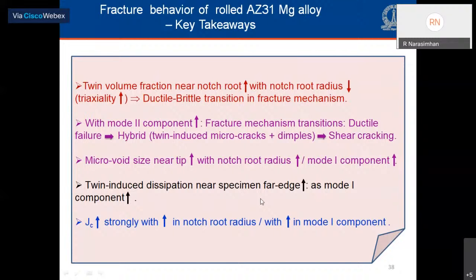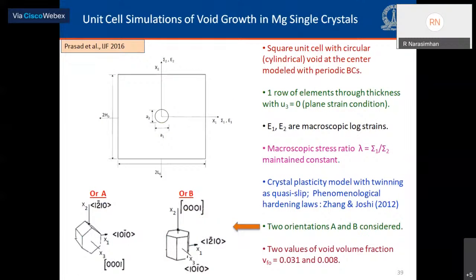I have summarized the key takeaways from this part of the work, but in the interest of time, I will just move further and show a few results from our finite element modeling, trying to understand how void growth and coalescence takes place in magnesium. And this again is restricted to single crystal simulations. The reason being, when you model single crystals, you can vary the lattice orientation very easily. And that gives you a perspective from the context of individual grains where the lattice would change. And we could understand it better.